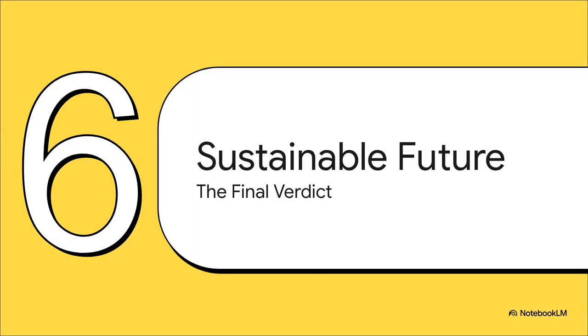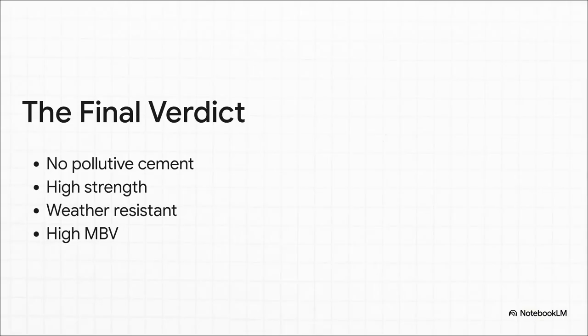Section 6. The future of sustainable building, the final verdict. We've looked at the chemistry, the rigorous erosion tests, the hygroscopic data, and the end-of-life recycling. Let's bring the final verdict together. The core takeaway from this extensive research is that we no longer have to compromise. We can eliminate the need for high-carbon, pollutive cement in earthen construction. By utilizing just 1.5 to 2.0% of natural biopolymers, we achieve excellent structural strength. These materials prove they can survive extreme weather, from heavy rainfall erosion in the Geelong Drip test to sudden floods in the Dip test. Unlike cement, they actually improve the indoor environment by creating breathing walls with high moisture buffering. And depending on your specific project needs, you can choose xanthan for peak strength or guar for ultimate easy recyclability.